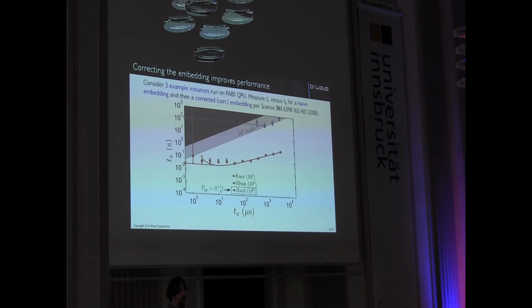You don't have to know that point in S, the anneal parameter, down to 6 digits of precision to find out where the phase transition is going to happen. You get it within 1 digit of precision. It's basically a correction that's good enough to impact solution quality. So if I go ahead and do those corrections as I've laid out in the supplementary information for that Science manuscript, then you get these bolder data that I presented here. Again, color coordinated with what you see there for easy, mean, and hard.